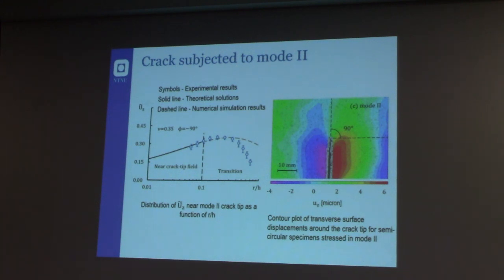These are the results that are the most original under mode 2. Actually we found that applying pure mode 2 to a component, we were also able to clearly distinguish a kind of displacement in the Z direction that is not predicted by any of the Irwin solution or Williams solution for the in-plane solution.